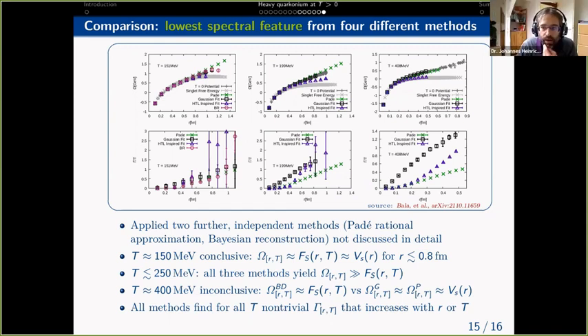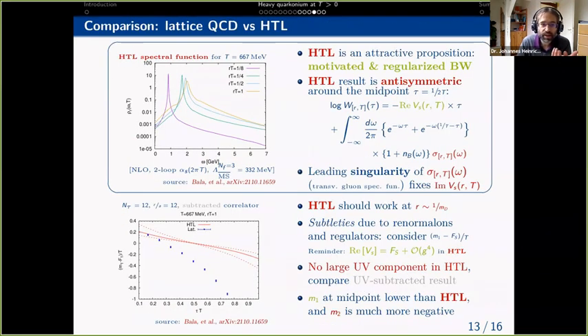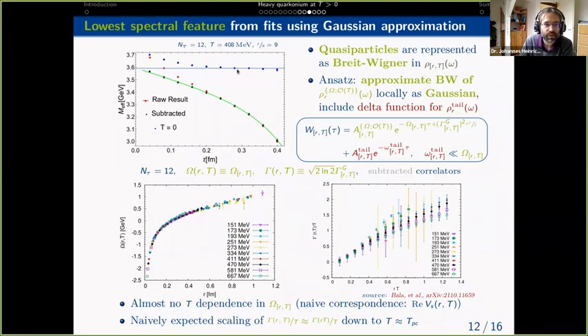One of the things we see is that the lattice data that we get are compatible with both scenarios. And the question that is not entirely clear is, if you look at this first cumulant or effective method you have here, whether the midpoint should be where you do the expansion, as you suggest by hard thermal loop, or whether you would do the expansion at 0 time. In this case, you get something that is manifestly close to 0 temperature, which you see in this figure. If you have the 0 temperature value of the effective meson mass over here, and you now subtract the V contribution, it must necessarily end up very close to here if you do this expansion here. But if you do the expansion somewhere over here, you see this gap immediately. So it's not yet something where we can say for sure which is the best choice.